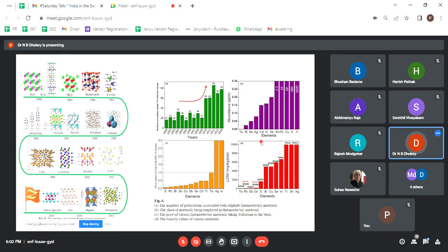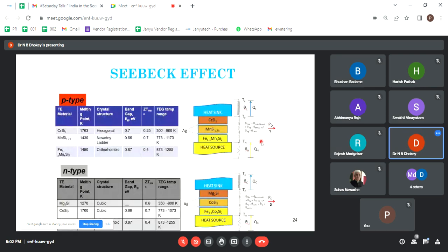And thermoelectric material is typically a semiconductor. In semiconductors, there are two categories. One is a low temperature semiconductor, like bismuth telluride. The other is like iron disilicide, a high temperature semiconductor, which can even go up to 900 degrees Celsius. But the whole problem in these semiconductors is the efficiency. The figure of merit is low, and therefore people are researching how to increase the figure of merit so that it will be an efficient thermoelectric generator. So this is a very hot area in the research domain.